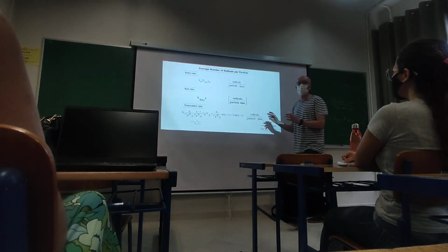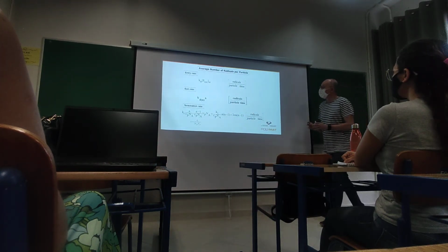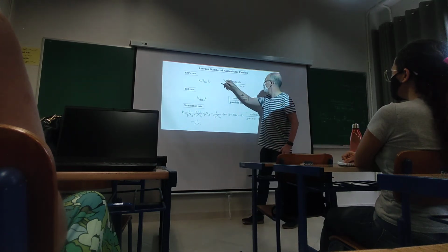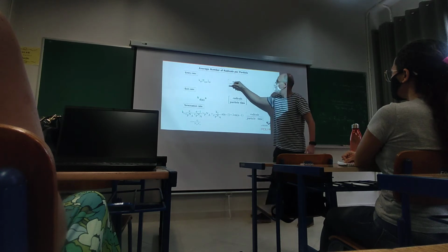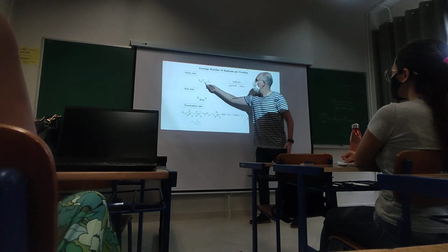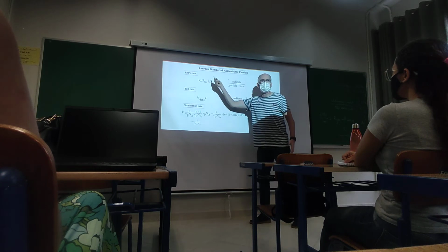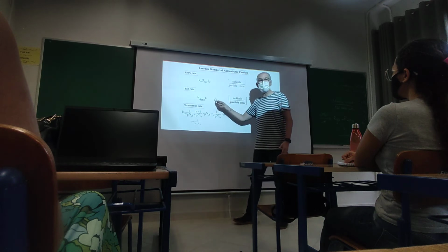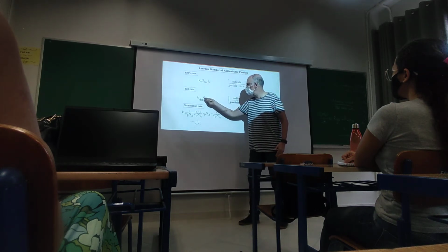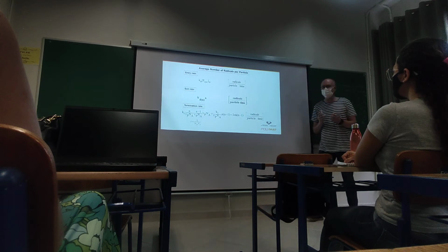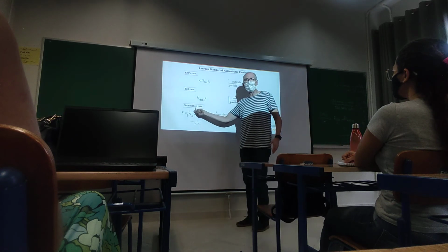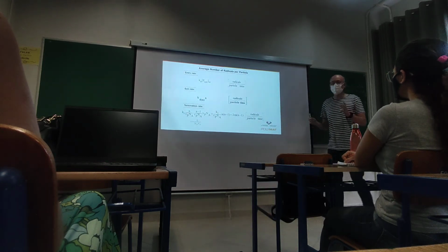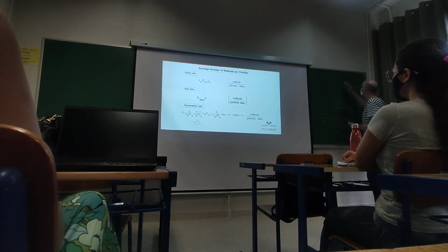So, before going to the balance, we will express the rate of entry, in seconds to the minus 1, as the frequency of entry, the absorption coefficient, times the radical concentration in the aqueous phase; the rate of exit as a frequency of exit, the desorption constant, multiplied by the number of radicals in the particle; and the rate of termination. We will express this as this, and this might look strange to you the first time.